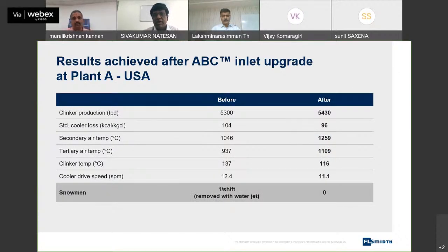So these are some of the parameters we achieved in multiple plants, where you can see the parameters before and after modification of the ABC inlet, and how they improved. You can see that secondary and tertiary air temperature increased, clinker temperature came down, and because of the better control in the fixed inlet, the bed depth control also got better, and we are able to achieve all the parameters at a lower cooler drive speed.